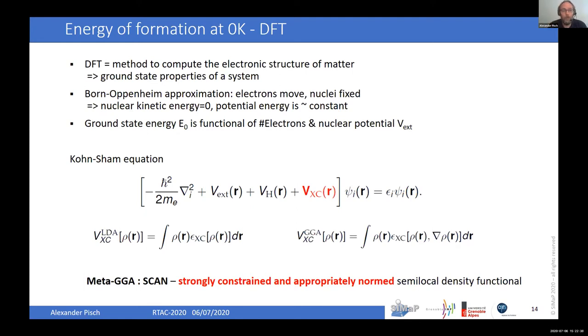To do this, we start from the Born-Oppenheimer approximation, where we consider only the electrons to move, and the nuclei are fixed. Then we try to solve the Kohn-Sham equation, which is here. In these Kohn-Sham equations, you have what is called the exchange functional. Classically, we have the LDA exchange functional and the GGA exchange functional. But more recently, since 2015, there is what we call the meta-GGA, which is called SCAN, strongly constrained and appropriately normed semi-local density functional. All calculations I will show in this presentation have been performed with this SCAN functional.